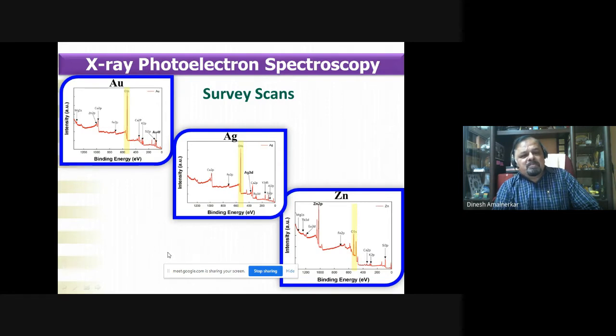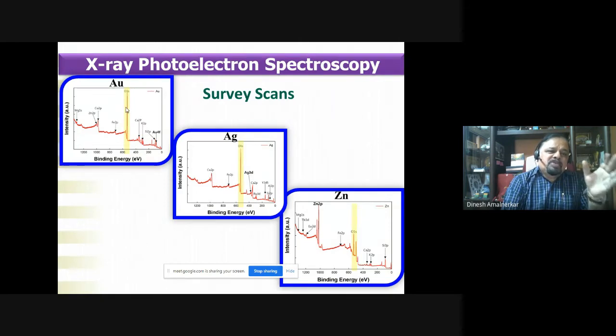And this is, of course, as per expectation. Unfortunately, my Korean student did not pursue further analysis of getting the high resolution scans, deconvolution. He has not done anything. I was unable to tell him in proper language what is needed further. But this was a surprise. You can't expect O1s to this extent in the X-ray spectra of any material unless there is a reactive oxygen involved in the compound. You can't expect atmospheric oxygen to give this kind of signal in XPS, because all of you know that X-ray photoelectron spectrometers operate at very high vacuum of 10 raised to minus 9 to 10 raised to minus 12 torr.